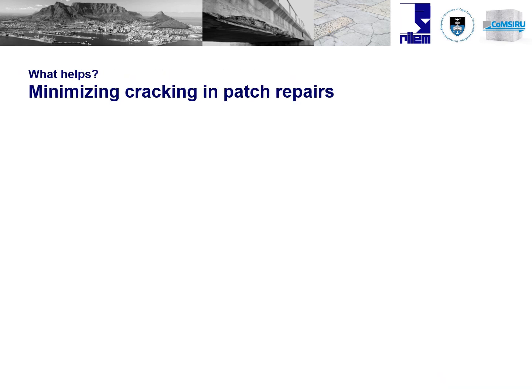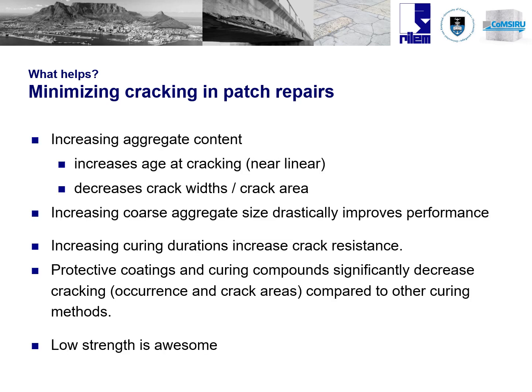In summary, to minimize cracking in patch repairs: increasing the coarse aggregate content has a huge effect on performance; increasing the coarse aggregate size also has a drastic effect due to crack mechanics; increasing curing durations improves crack resistance; and in particular, protective coatings and curing compounds significantly decrease cracking and crack areas. Largely, low strength is good — we don't need high strength in our repair mortars.